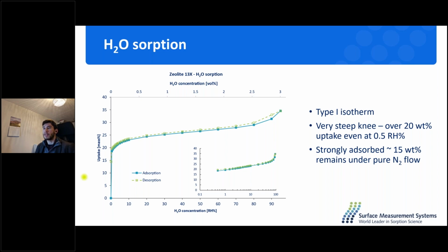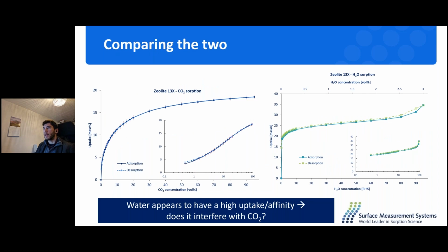One thing to note is that relative humidity corresponds to a much lower volume percent concentration. So if we think about 100% relative humidity, that means 100% of the capacity of a carrier gas to carry water at that temperature. So at 25 C, 100% relative humidity corresponds to around 3% by volume. So just one thing to note is when we're comparing two isotherms, relative humidity and CO2 with volume percent, it's not exactly apples to apples.